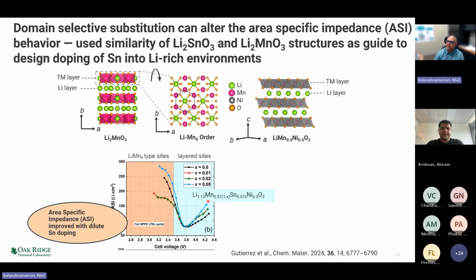We believe that the area-specific impedance in the blue region is controlled by the layered component of this complex material, while the region here is controlled by the Li2MnO3 activated regions, the regions that are developed from the Li2MnO3-like structures. So if we are able to dope tin into these regions, we have a chance of disrupting or changing the behavior in those regions. That was the goal of the study. And indeed, what we find is that when you put a small amount of tin dopant, we can significantly reduce the area-specific impedance. Now, while the dopant is put in, and our aim was to make sure that the dopant sits in these lithium-rich Li2MnO3-like regions, we needed to prove that that is the case.